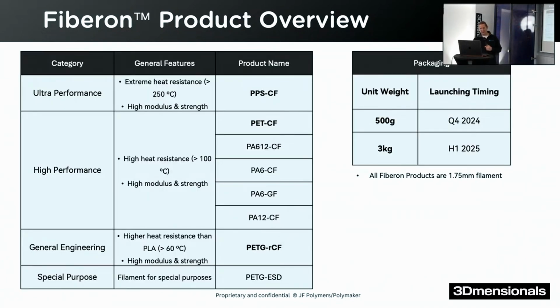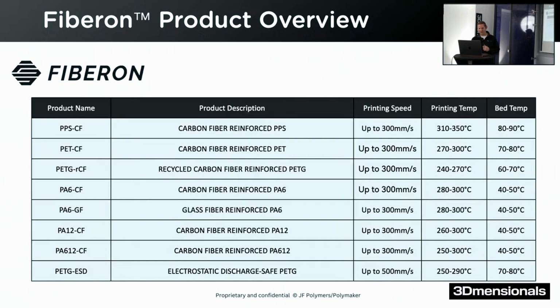So we split our materials into 4 categories. At the top here we have the ultra performance, which is our new material. It's PPS CF, and then we have a high performance, which is like materials which have a heat resistance over 100 degrees. This is a heat deflection temperature with high modulus, high strength. Then we have general engineering, which is higher heat resistance than PLA, but with added stiffness. And this is our PETG RCF. What's interesting is we have a recycled carbon fiber. And then our special purpose filament, which is right now our PETG ESD. And this is actually using carbon nanotubes instead of carbon fibers, but I'll share more on that later.